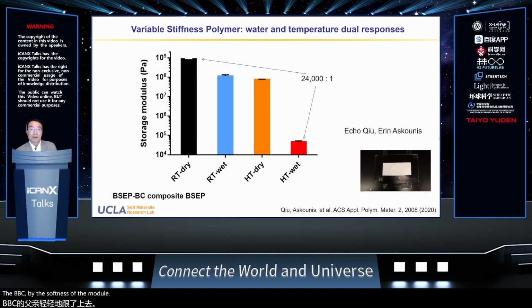So the modulus drops by about 1 order of magnitude. When it's heated to above the transition temperature of the BSEP, it softens, also by around 1 order of magnitude. If it's heated and water soaked, both the BC network and the BSEP network soften. So the modulus of the composite drops to only about 10 to 40 kilopascal. So overall, the modulus variation here is 24,000 times. A very large modulus change from this system.